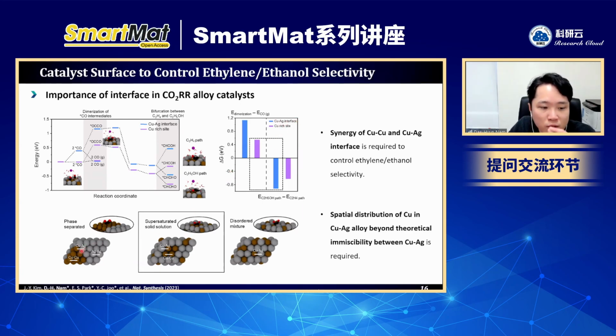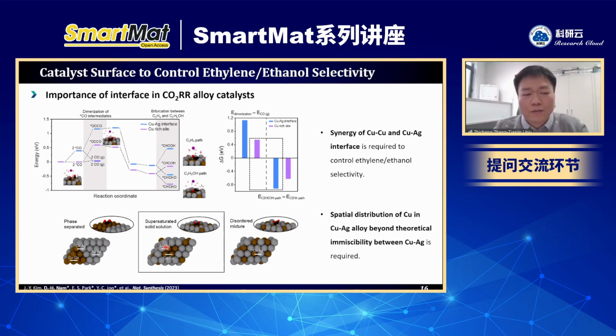If we make it phase separated, there can be a lot of copper, but there will be fewer copper-silver interfaces. But in the case of the uniformly mixed one, there can be a lot of copper-silver interfaces, but less copper. So this would be beneficial for the transition to the CHO pathway, but this will lower the portion of C-C coupling. That is the reason why I mentioned we need both copper and copper-silver simultaneously. So that is why we try to focus on partially mixed copper-silver, with some parts separated. Yeah. Okay, thank you. Thanks for your reply.